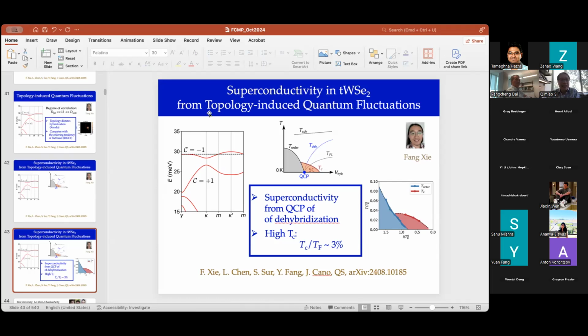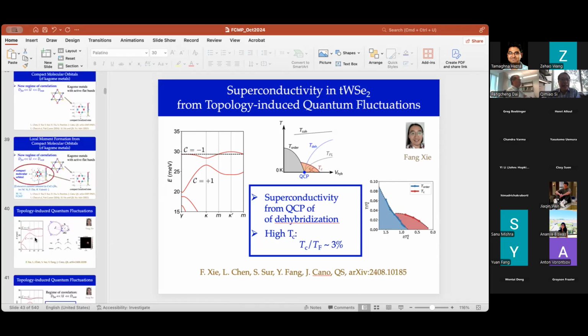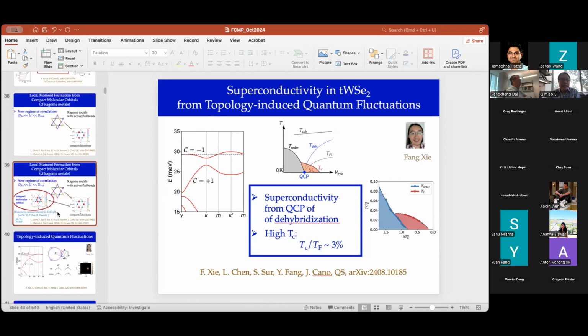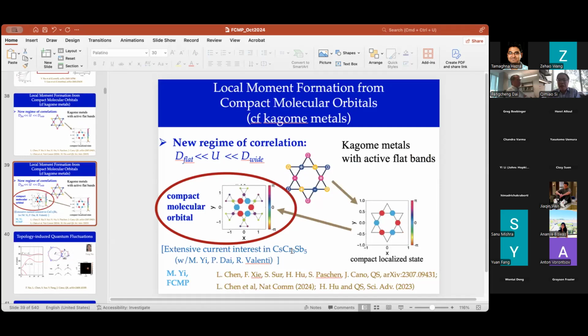In fact, if you look at this new Kagome material, it's on my slide, this cesium chromium 3 antimony 5, the superconductivity is happening under pressure. So I think for the cobaltates that you mentioned, it would be good if there's some understanding of, say, ARPES, to see whether the flat band is there. And there's also the three-dimensional pyrochlore material, lithium vanadium 2 oxygen 4. It seems like also will be opportune to study the electronic structure and you don't necessarily need ARPES.